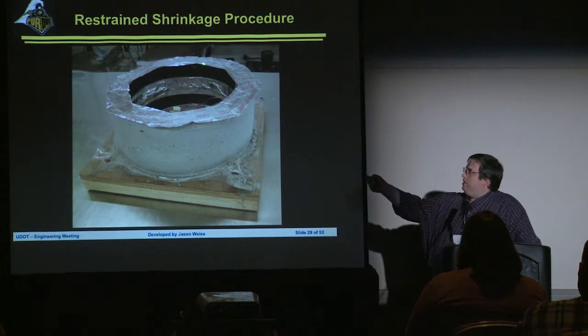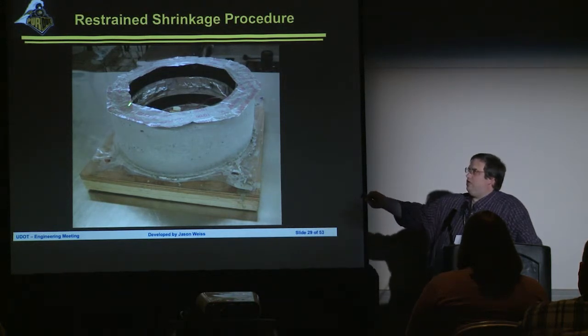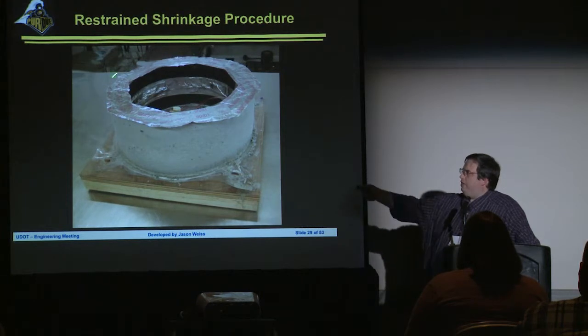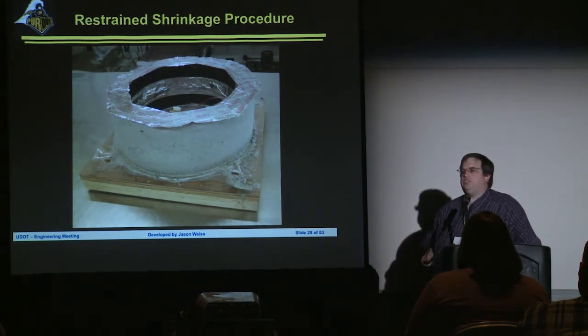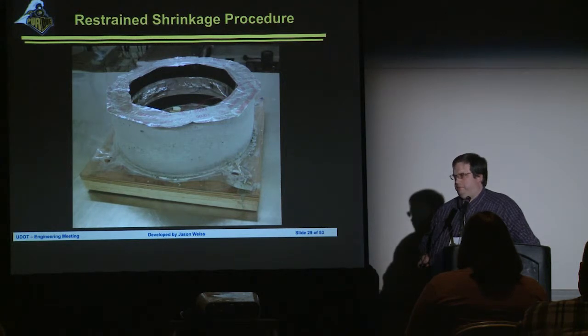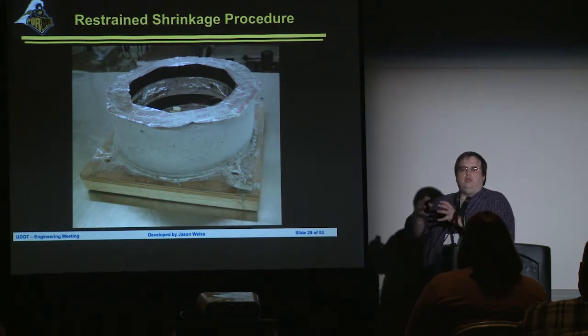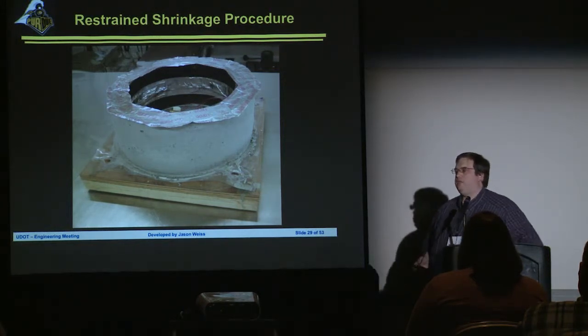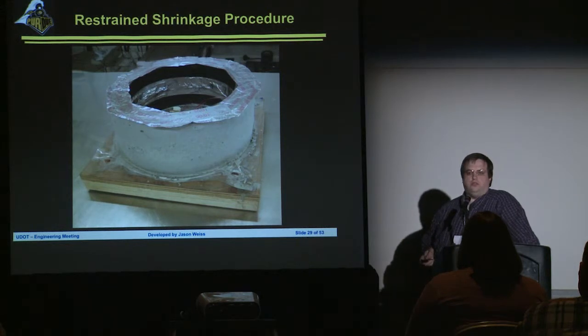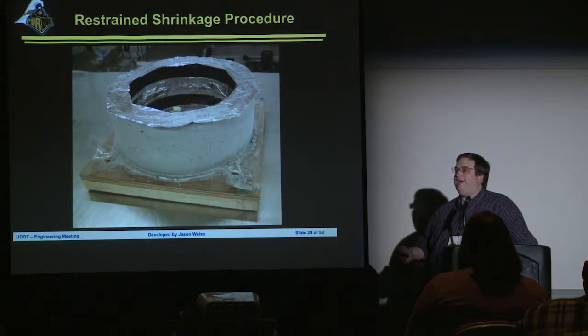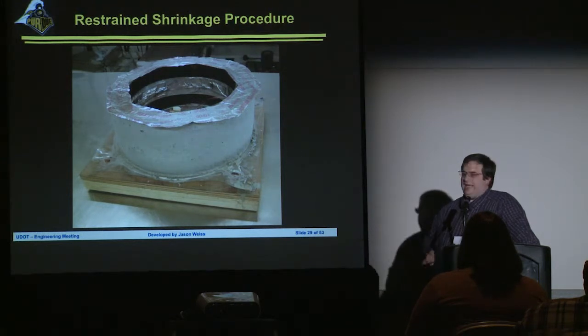Well, we've got a steel ring on the inside, and that steel ring has strain gauges on it. We place concrete around that ring, and if the concrete wants to shrink and get smaller, the steel prevents that from happening. So the concrete says, I want to shrink and get smaller. The steel says, no, I'm going to restrain you. I'm not going to let you move where you want to move, and it pushes back. This is a lot like what girders do to a bridge deck. The bridge deck says, I want to shrink and get smaller. The girder says, it's not going to happen. Stresses build up inside of the concrete. And if the stresses build up to a high enough level, you can get cracking. Now, we may look at this and we may say, well, this doesn't look anything like a bridge deck.